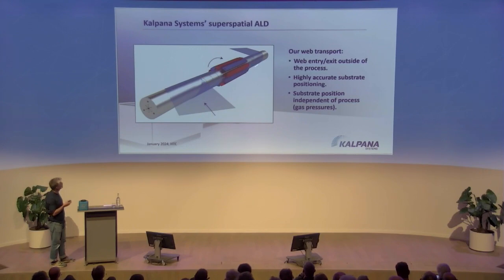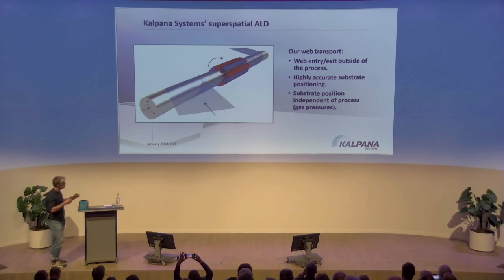So this is actually what we do. We have a web transport mechanism in which we transport our substrate in a helical manner, very controlled. And in this way, we first of all don't have the web entry and exit inside the process, so we can have it very stable. And on the other hand, we can have a very highly accurate substrate positioning.